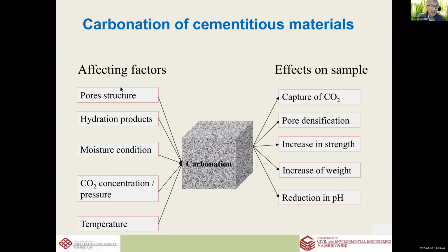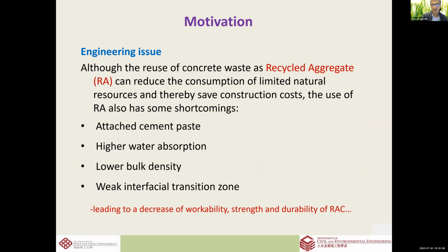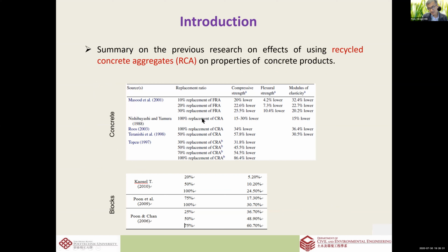Okay, sorry about that. There are a number of factors affecting carbonation: the pore structure, hydration product, moisture condition, CO2 concentration, and temperature. We are very interested in understanding how a recycled aggregate can be carbonated, because the recycled aggregate itself, as I said, has inferior properties to a natural aggregate because of the attached cement paste or mortar, leading to high water absorption, lower bulk density, and a weaker interfacial transition zone. With that, when we make recycled aggregate concrete, the recycled aggregate will lead to poor workability and also lower strength and lower durability.